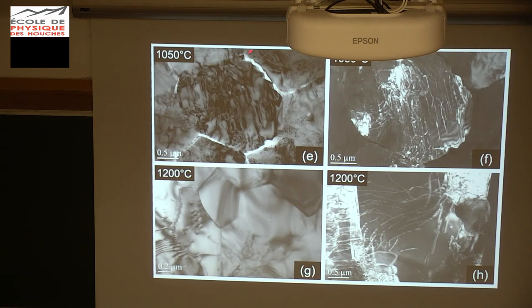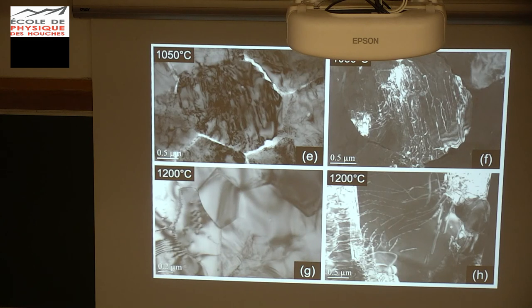You have those steps or teeth or whatever, but we haven't yet proved that they are crystallographically controlled. We're suspicious about that, but what we have now is not that clear. At 1200 degrees Celsius — no gaps, no teeth, no asperity, no cracked grain boundaries. We go back to very classical, geologically relevant features: tight grain boundaries and dislocations in the convecting part of the Earth.